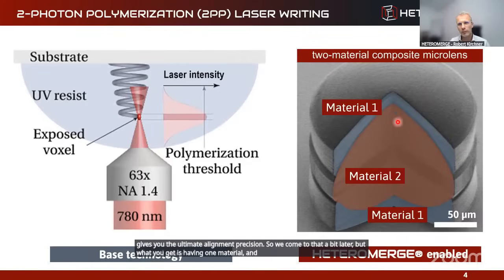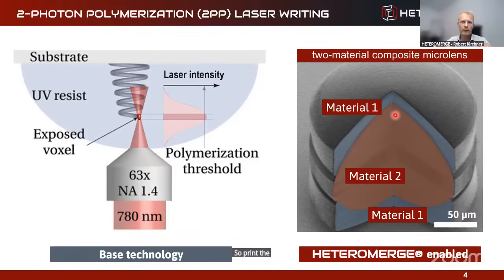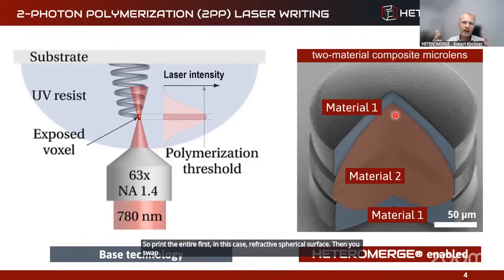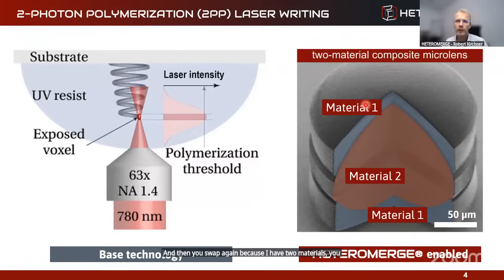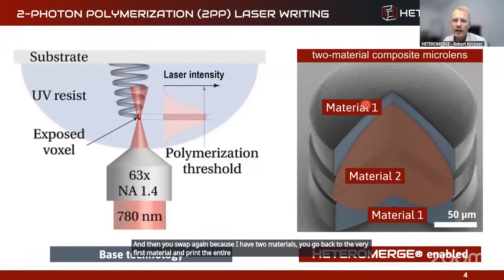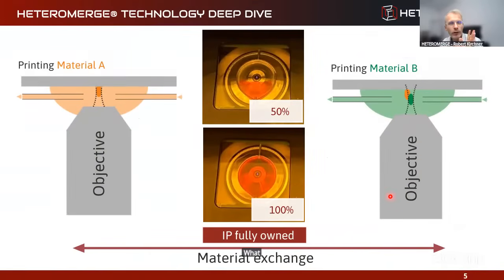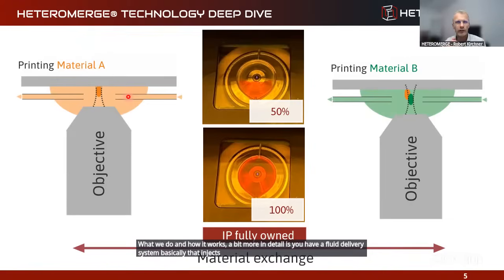If you think about a triplet of 2 materials, you have the first material for the first lens. So print the entire first, in this case, refractive spherical surface. Then you swap the material, you print the entire second lens, which is the central core of the triplet. And then you swap again, because I have 2 materials, you go back to the very first material and print the entire third lenslet. And that is perfectly aligned on the optical axis. All right, so this is what we do and how it works. A bit more in detail, you have a fluid delivery system that injects liquid into this immersion situation.